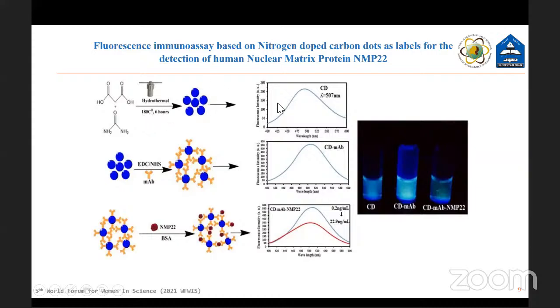Then we check the fluorescence of the nanoparticle. After that, we conjugated this nanoparticle with EDC, NHS, and our antibody, which is specific for NMP. That antibody is abbreviated as MAB, which is called monoclonal antibody. When we conjugated this antibody to our nanoparticle, we saw the enhancement of fluorescence, as it's clear here, which indicates the conjugation of antibody to our nanoparticle.